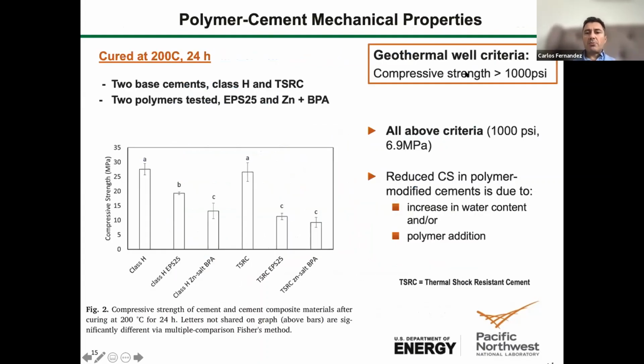After 24 hours, for geothermal wellbores, we need a compressive strength above 1000 PSI or 6.9 megapascal. All of these polymer modified cements have a reduction in compressive strength as compared to control cement H or the thermal shock resistant cement, but all of them have a compressive strength after 24 hours above the requirement, between, I would say, 1500 PSI all the way to 3000 PSI, just after 24 hours. The compressive strength obviously increases as the material continues hydrating over the days.